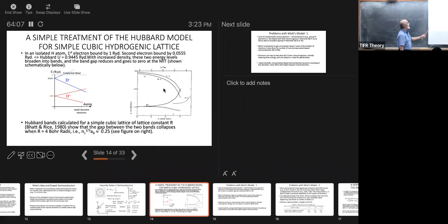So it's there. Now, as you increase the density, these bands will broaden because there's hopping. But the important thing is that these two bands are split. These are two split bands starting from zero density, unlike in band theory, where up electron and down electron have the same energies. Now, you can't quite call it up electron and down electron. This is singly occupied, that's doubly occupied. But you can sort of close your eyes and say that the down spins have lower energy and the up spins have higher energy.